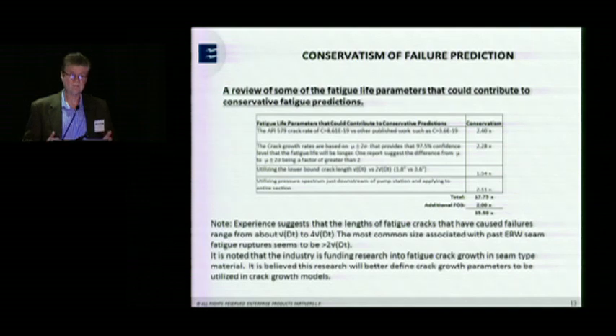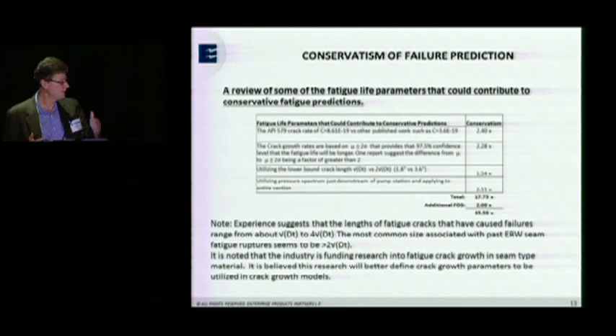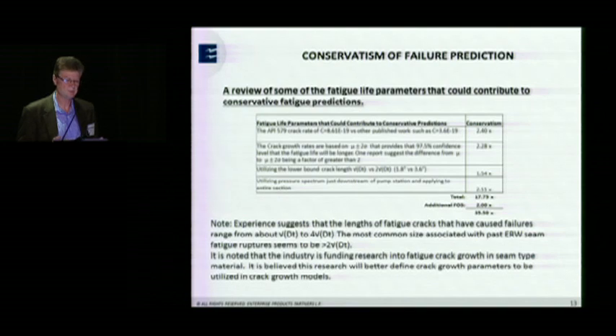And the other thing we have to remember is that when we're using these formulas that people have put in API and other standards, they're not based on the mean. They're based on the mean plus 2 standard deviations. They should be, but remember there's conservatism built into that model. And I looked at some of the data out there, and from the mean to that 2 times the standard deviation, there's over a 2 times factor of safety, and sometimes it can be much larger.